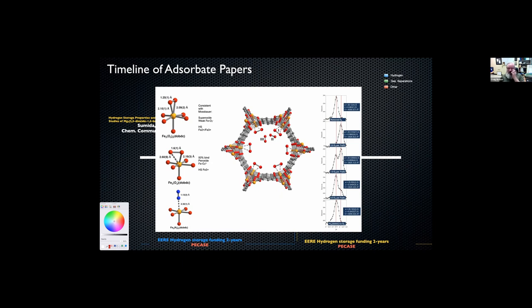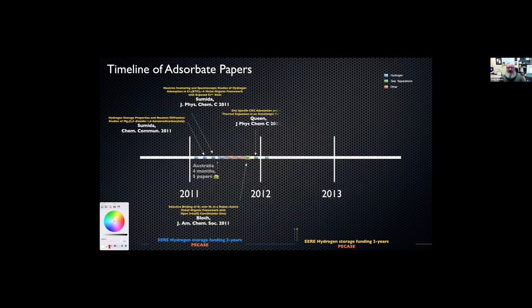it really is a cooperative adsorption. When the oxygen's in one unit cell, you can see on the right-hand side, these are the same Bragg peaks for the entire system. But one particle is pulling in oxygen and there's a cooperative adsorption of oxygen in that one particle. And it's completely reversible in this system. That was pretty neat.